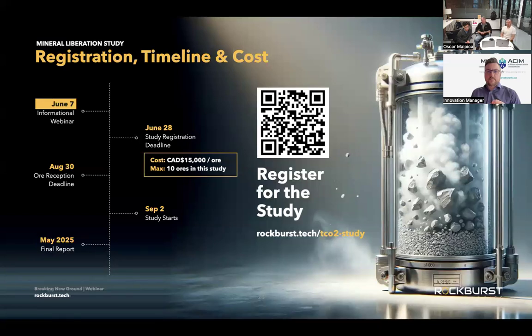We've been limited in size by our prototype equipment, which is not that large. We could fit probably a 3-inch rock into our alpha prototype, but it wouldn't mean much because we'd only fit 1 or 2 in there, and then you don't get representativity of the ore, because ore is so heterogeneous that you need to process a lot of particles at the same time to get a good representation of what that result is going to be. So we've tended to use smaller particles in our prototypes.